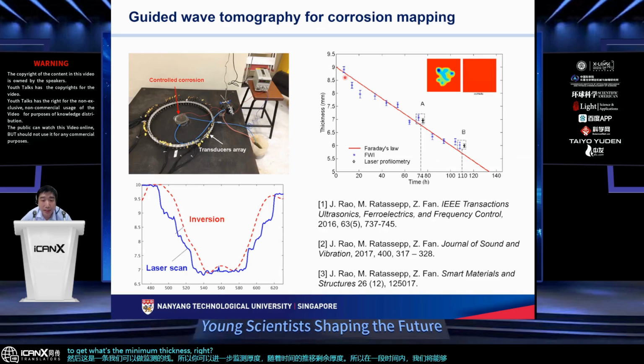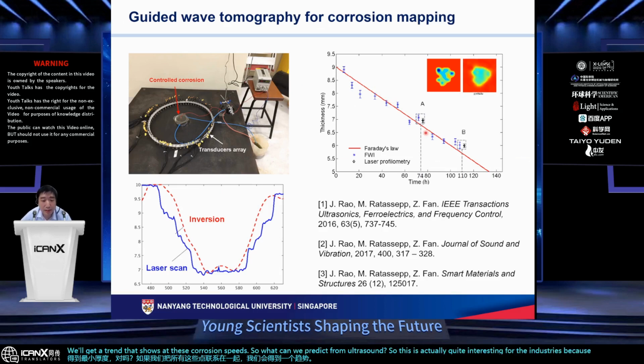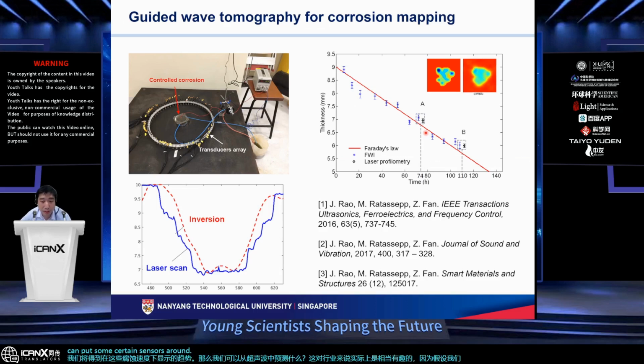And if we connected all these points together, we'll get a trend. We'll get a trend that shows, at these corrosion speeds, what can we predict from ultrasound? So this is actually quite interesting for the industries, because assuming that we can put certain sensors around certain regions that are able to tell the corrosion rate, meaning the reduction rate, that can potentially give industry some useful information, like how long your pipeline can last if it is under a certain corrosion rate, right? So if this technique works, that can potentially help the industry.